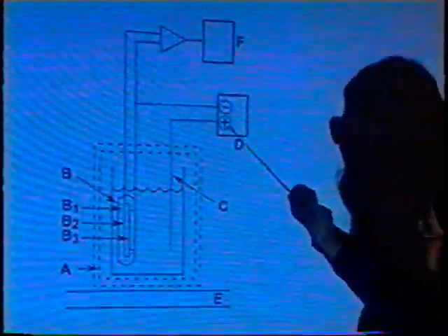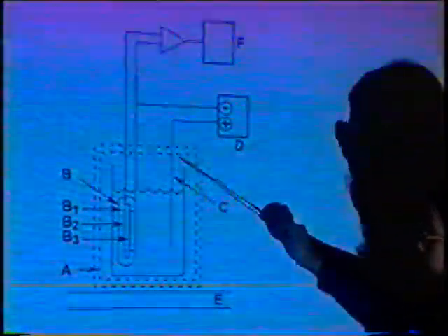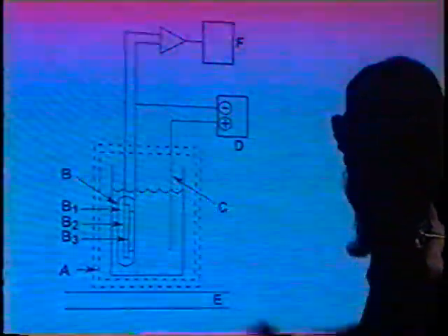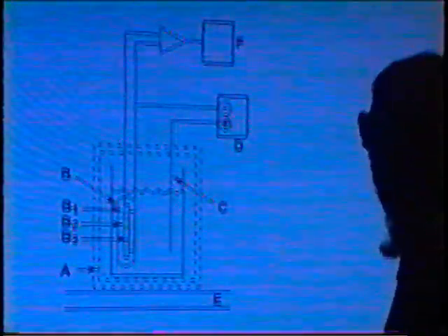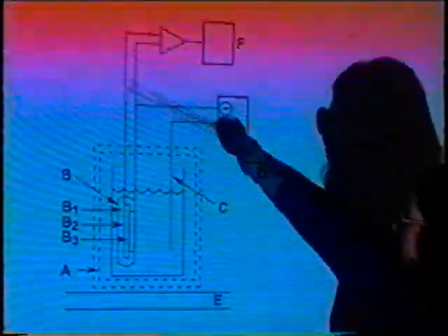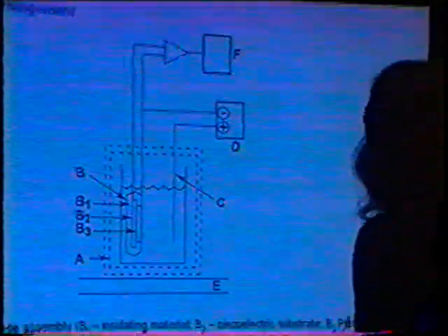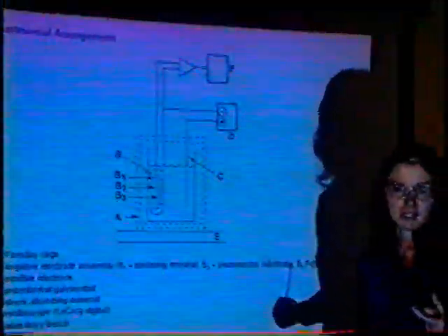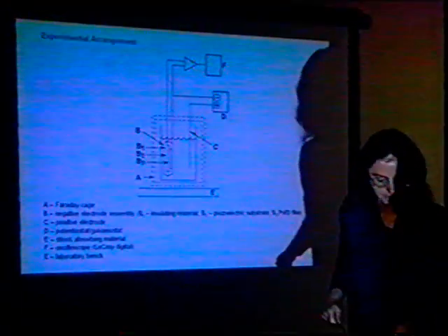We have a potentiostat to control the voltage, or the current, between the counter electrode and the silver on the piezoelectric crystal. And then we have the leads from the piezoelectric crystal going to an oscilloscope where we measure the voltage difference. And that voltage difference would be proportional to the constriction and expansion of the crystal.